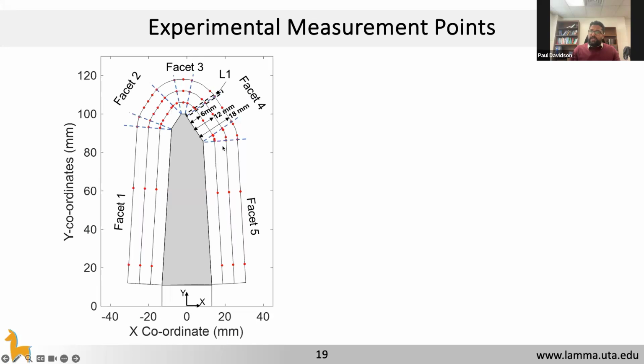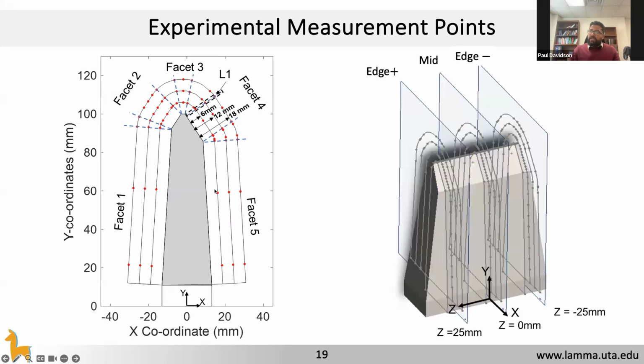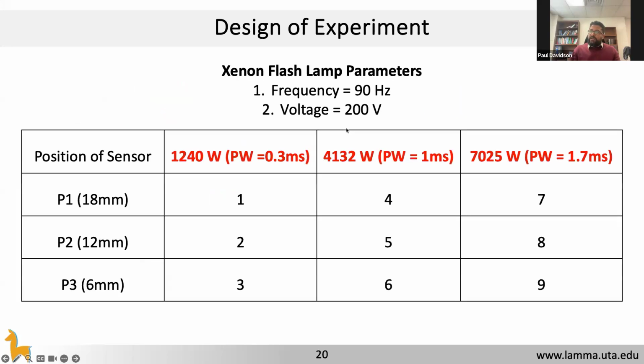So to do that, we created a grid, and this is all at different lengths. So it is 6, 12, and 18 millimeters off from the facets. And then we looked at three planes of measurements. That is the mid, the positive edge, and the negative edge. And then we essentially ran a DOE to look at how different power values and different distances influence our readings or the parameters of incident radiation.